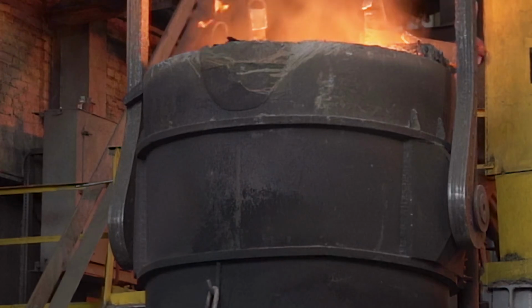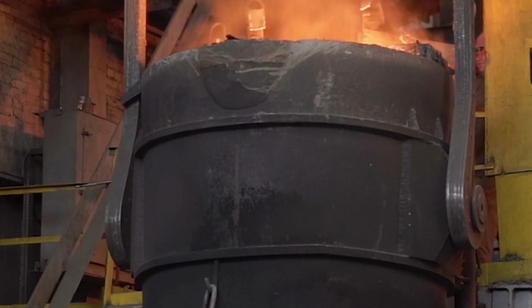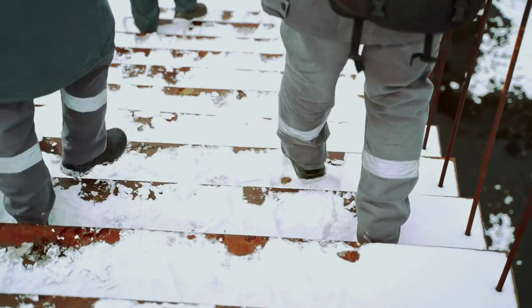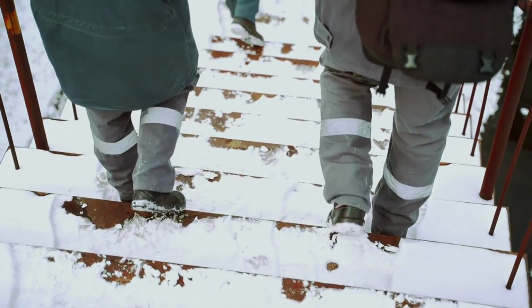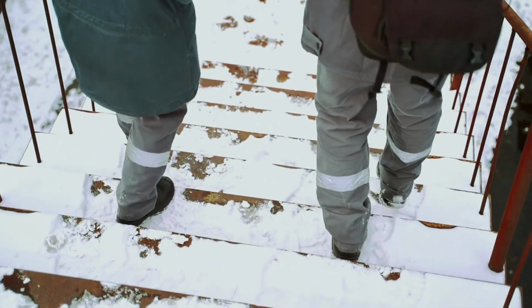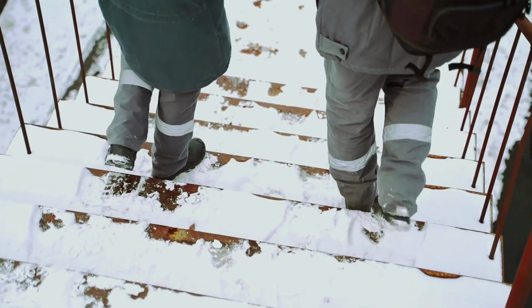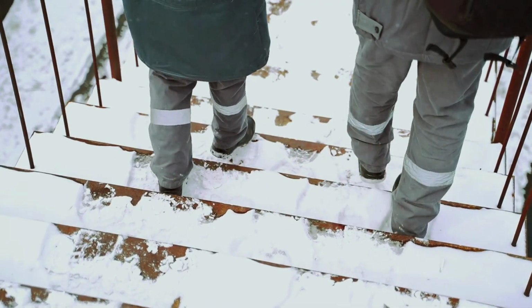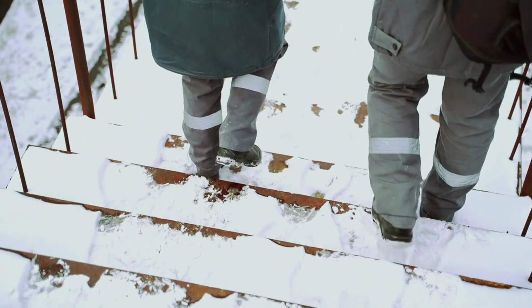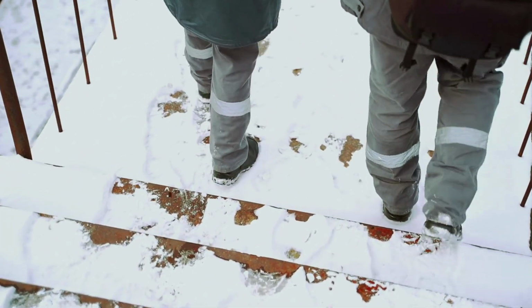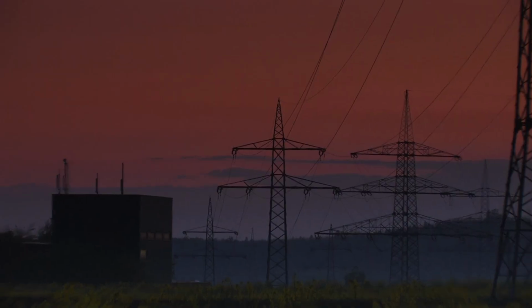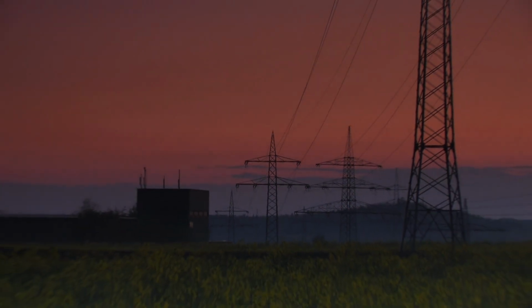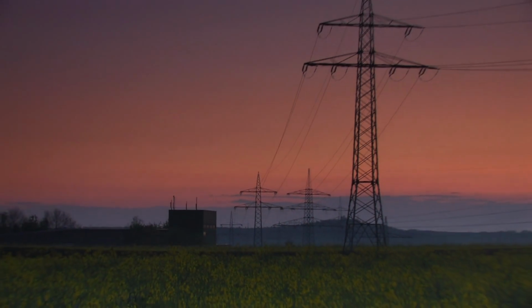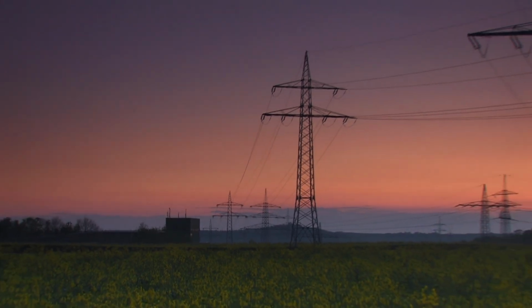Pittsburgh, 1953. Inside a steel mill, a ladle holding 175 tons of molten metal moved slowly overhead. The workers below barely looked up. They had walked under that same crane hundreds of times. The steel glowed white at 2,900 degrees Fahrenheit. The ladle hung from a single hook, and the system was storing a failure it could not contain.